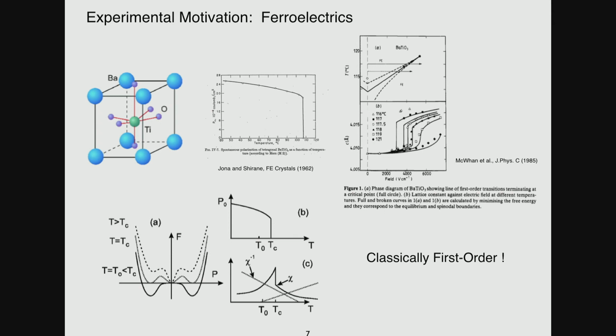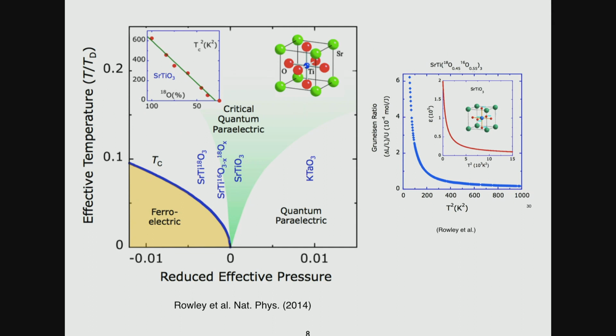Well, several people, including the Cambridge group, also the Paris group, decided to look at these materials at low temperatures. Now, strontium titanate is a close cousin of barium titanate, but unlike barium titanate, it does not go ferroelectric. It has a dielectric susceptibility that's big, big, big, but it never actually diverges, it saturates. However, it's so close to a ferroelectric transition that if you take strontium titanate and replace oxygen 16 by oxygen 18, you can drive it ferroelectric, okay?